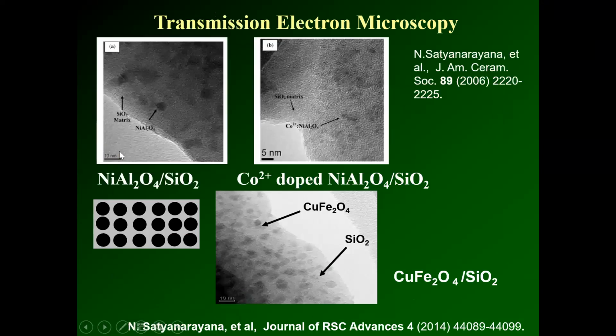Now we can see that in the 10 nanometer range we have taken nickel aluminate. These black spots are the spherical nanoparticles of nickel aluminate. Gray is the amorphous SiO2. Here, cobalt nickel aluminates are in the range of 5 nanometers. You can see the spherical particles of cobalt nickel aluminate nanoparticles.